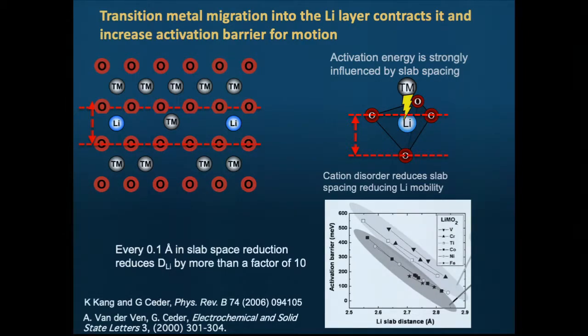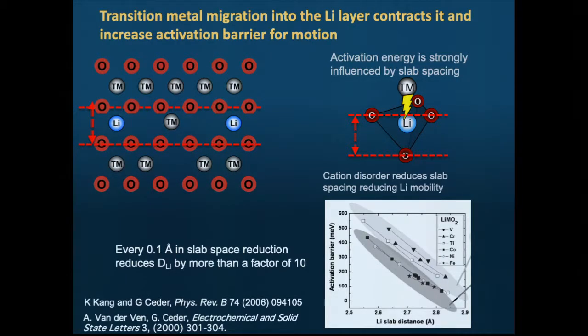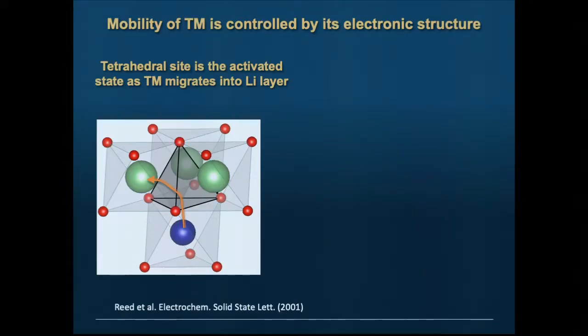And as engineers, you should learn to appreciate the numbers. If you put something in an Arrhenius factor at room temperature, every 56 milli-electron volt causes an order of magnitude change in the Arrhenius factor. And here, to get 56 milli-electron volt, the slab has to change by only 0.1 angstrom. So you only get a change in lattice parameter of 0.1 angstrom, and you lose an order of magnitude on mobility. Okay.